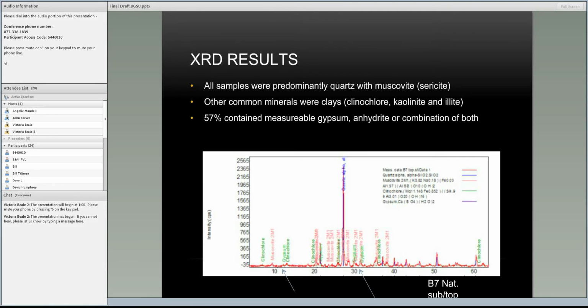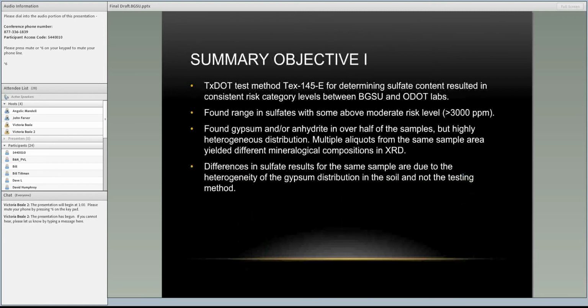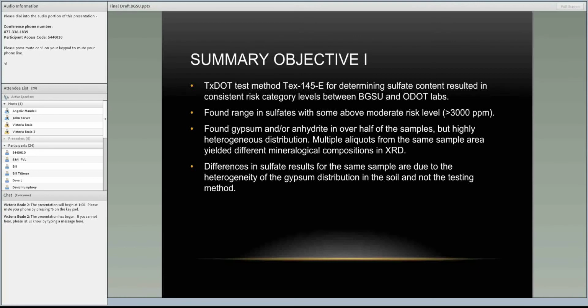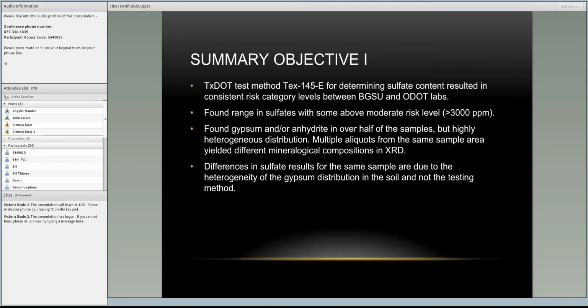Okay, so a summary of our objective 1. We determined that the Texas method was the preferable method to use when sulfate testing, and that between the 2 labs, BGSU and ODOT, our sulfate results for the boring samples were pretty consistent. We found a lot of sulfates in the boring samples above the 3,000 parts per million risk, and we also found gypsum and anhydrite in over half of the samples. But as you'll see as we go on through this talk, gypsum is very heterogeneous in the soil. You can find it a lot in some samples and not at all in others. It's not evenly distributed through the soils.